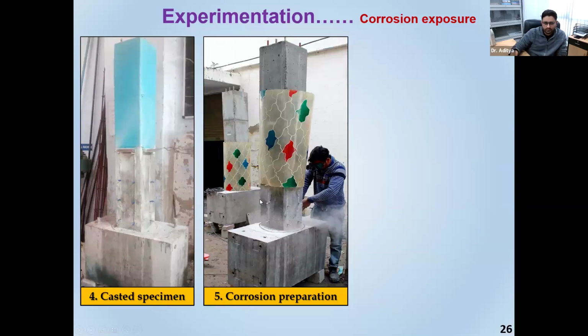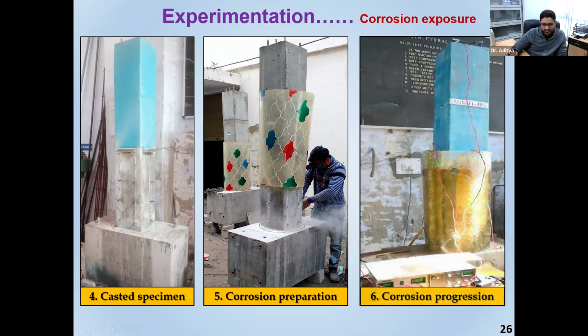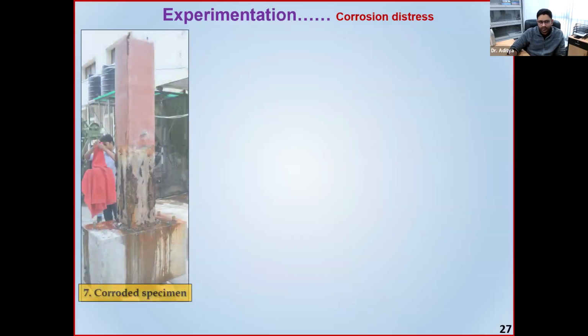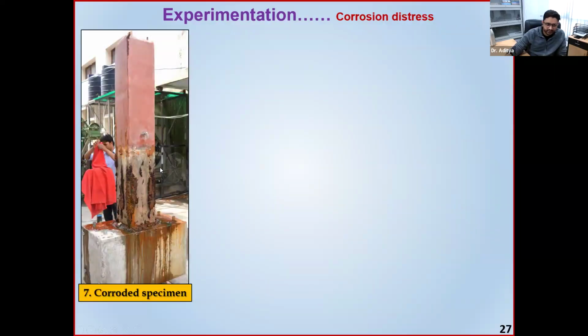Then we prepared it for corrosion. Then the corrosion was started. You can see over here, sodium chloride solution has been given. These are external DC machines. There's this entire setup for the external corrosion that is given, which is called the impressed current-based technique. After corrosion, you can see over here, this region has suffered a significant amount of corrosion. These are corrosion byproducts, which you are seeing over the surface of it.